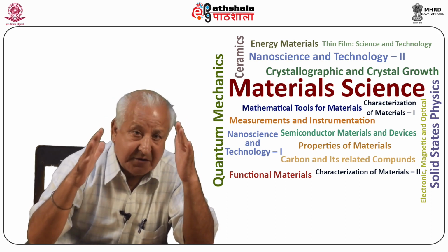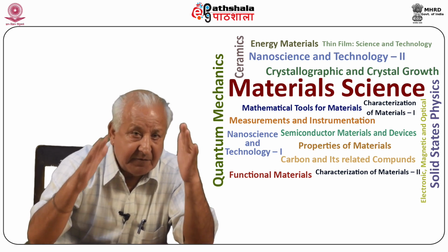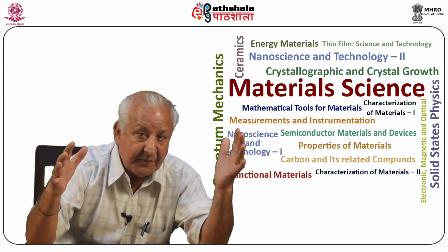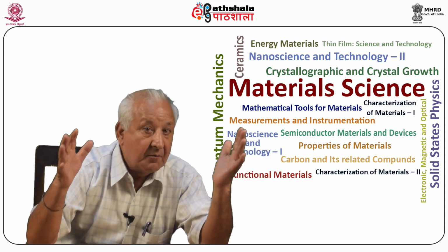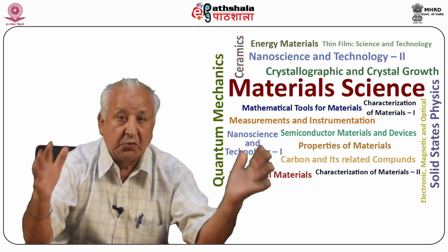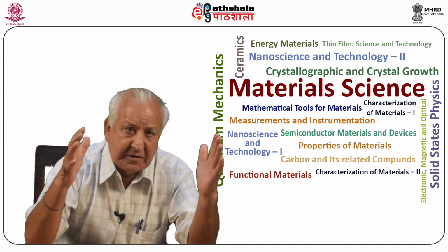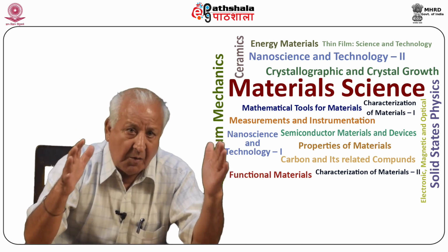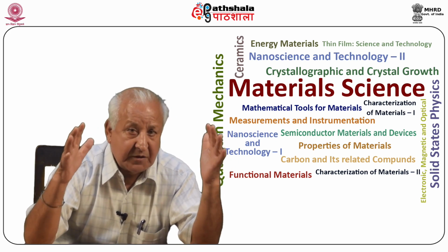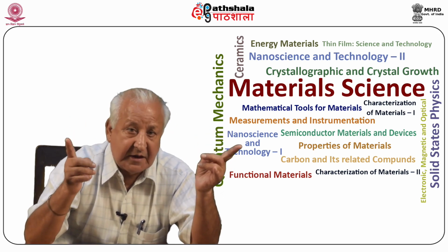That in the body-centered cubic structure, certain h'k'l' reflections which are present in a simple cubic structure bearing the same cube edge dimensions are missing can be physically understood by referring to figure 14.2. As an example, for BCC structure, there is no 100 reflection, but 200 reflection does take place. Similarly, there is no 111 reflection, but 222 reflection is present. Let us take into consideration the 100 reflection first. For simple cubic structure, the beams reflected from the top and bottom cube faces of the unit cell are in phase, out of phase by 2π, for the 100 diffraction direction. This is not so in the case of body-centered cubic structure.